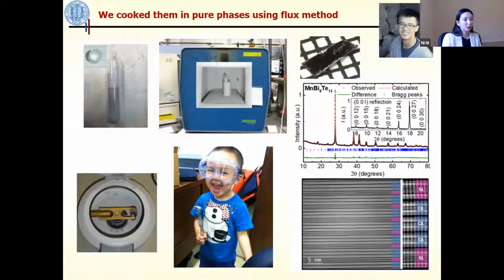So it's time to cook, right? We use the flux method to grow the sample. We mix the elements and seal them under one third of an atmosphere of argon. We put it in the furnace. After the synthesis, we spin out the liquid from the single crystals. And the most important part is we need to have a very happy, patient graduate student with a magic hand, right?